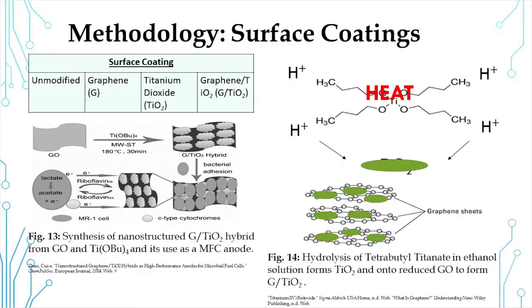The capillary action test was conducted where the anode was submerged in a liquid in order to assess relative surface area. Then scanning electron microscopy was used to visualize the anode morphologies. In phase 2, we evaluated hybrid surface coatings in order to use graphene's high electrical conductivity and titanium dioxide's high chemical stability. The composite was synthesized using a one-pot solvothermal method based on works of Zhao. So this is the process of how we synthesize the composite.